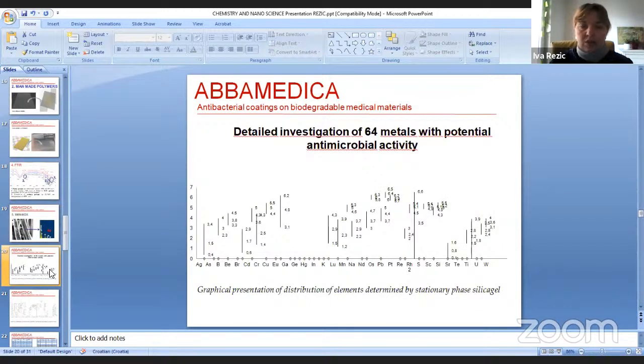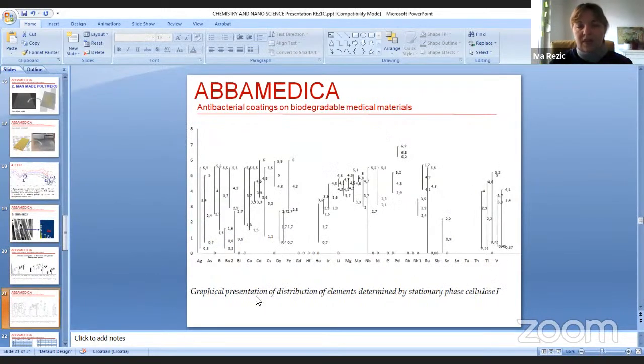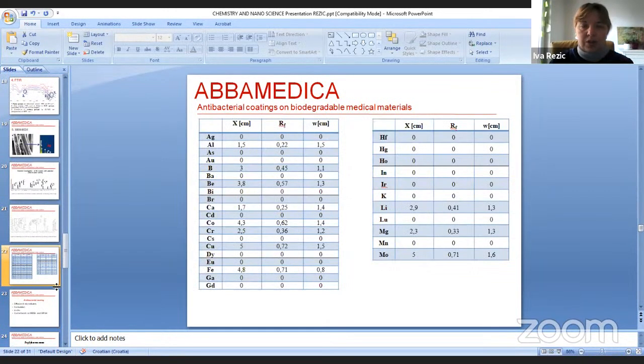So when we have proof which nanoparticles are present on the surface of the polymer, we can try to see what is extracted. So for this, we are currently in the process of development of a chromatography procedure in which we test 64 different metal ions with different, as you can see, stationary phases, different mobile phases, and we are monitoring the ranges where the spots of the samples are occurring on a plate, and this is ongoing research for now. So what we can measure actually is the retention factor. This is actually the place where a particular metal ion has moved when it's carried by a mobile phase on the plate.